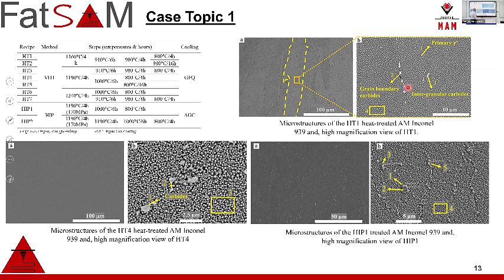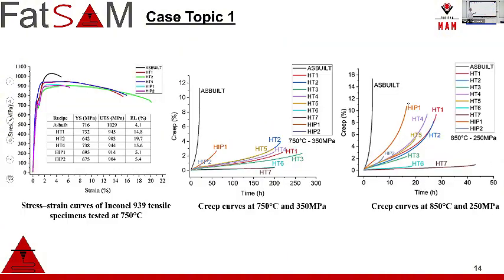In terms of HIP plus vacuum heat treatment procedures, again, there is some shadow effect of melt pool boundaries, not newly oriented grain boundaries. In the melt pool boundaries, we again have carbide phases, but much finer compared to vacuum heat treatment, and gamma prime precipitates. When we look at the mechanical properties, after improving heat treatments, we have better tensile properties even at high temperatures.